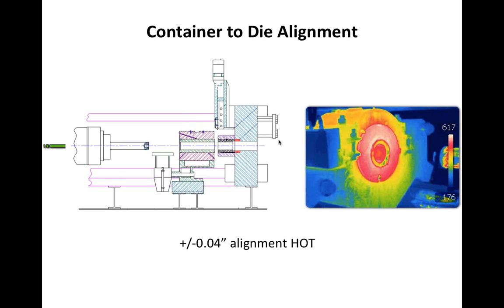And again, we have 40 thou here instead of 60, which I prefer. You can see in the thermal image on the right-hand side that in this case, the container housing is hot, and the top of the container housing is about 100 degrees hotter than the bottom. So we have a lot of things going on here that we hope not to see.